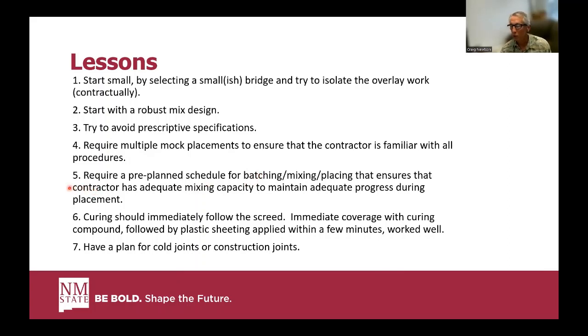Ours could have gone smoother, but that was largely due to the contractor. It's a combination of the size of the project and the contractor's capacity. On the actual construction, the curing really has to follow immediately behind the screed. Curing compound down immediately behind the screed, and the plastic on the curing compound no more than a handful of minutes behind that. And then have a plan for cold joints or construction joints.